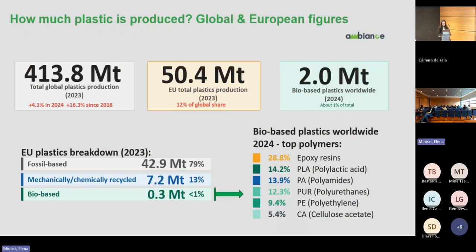Now, speaking about some numbers, the total global plastic production in 2023 was 413 million tons. That is a really huge number and it's still growing. Speaking about Europe, in 2023 we produced 50 million tons of plastics. And worldwide, the amount of bioplastic produced in 2024 was 2 million tons. So the share of this quantity is around 1% or less. We have the same situation in Europe in 2023, where 13% of plastic is recycled and less than 1% is bio-based.